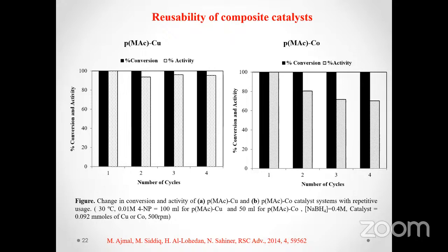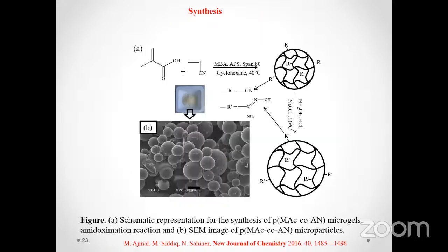And then there were various options: we could change the metal salts, the stabilizers, or the reducing agents. Among these various options, we selected one: that we should co-polymerize methacrylic acid with another system, because the literature says that if we have amidoximes in a polymeric network, then it can bind the metal nanoparticles strongly, and the mechanical stability of the system is increased.